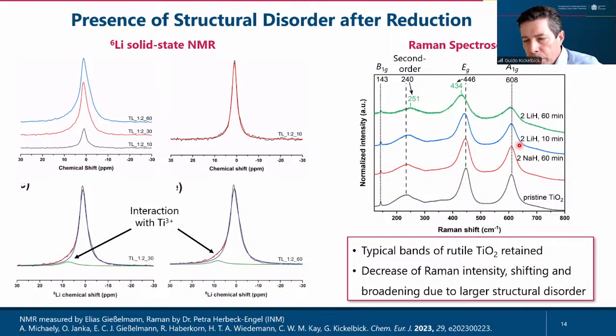In addition, what you also can do in the solid is look into Raman spectroscopy, because mechanochemical treatment usually gives you broader peaks and sometimes also peak shifts. And this tells you also something about the structural disorder. Here you see clearly that in the case of sodium hydride, you have nearly none of such shifts. But in the case of lithium hydride, you see that there is a large shift in this region. Okay.